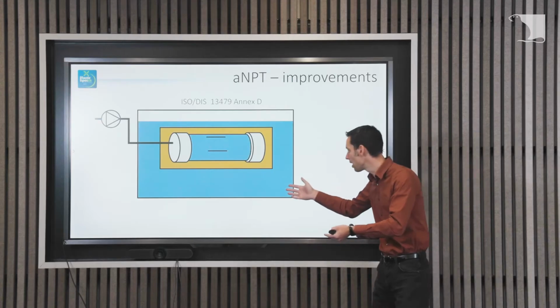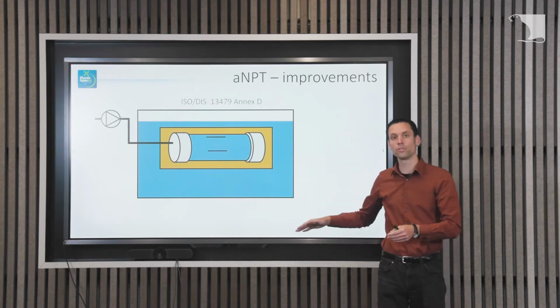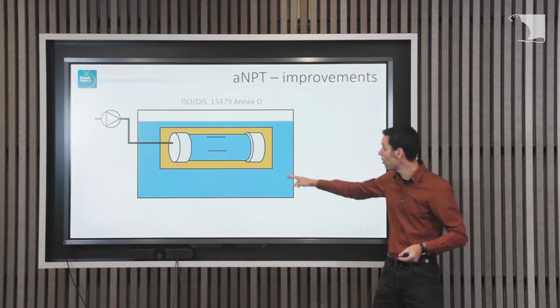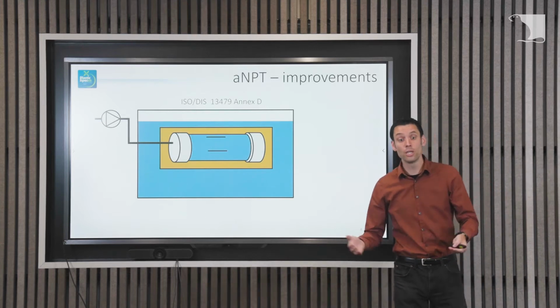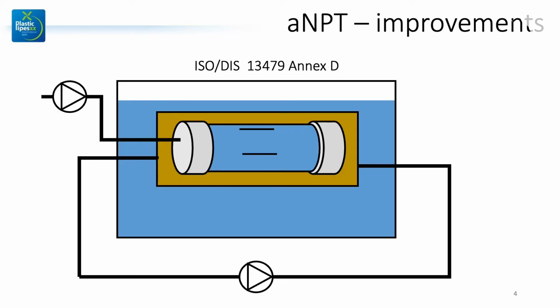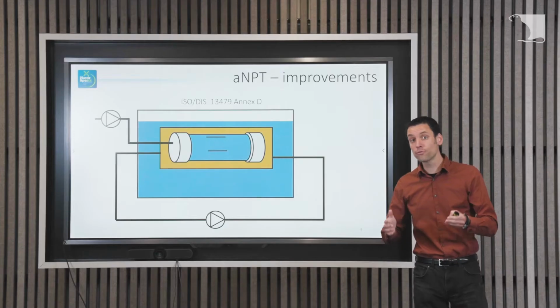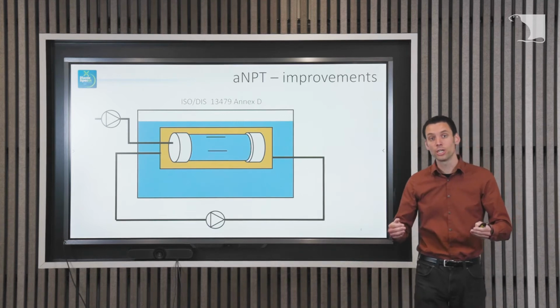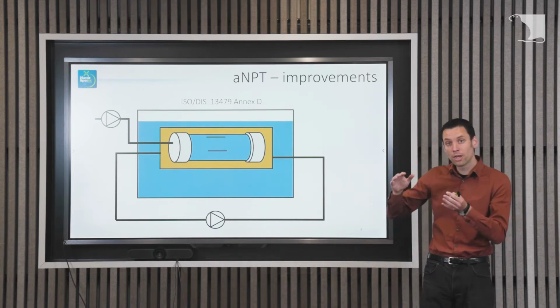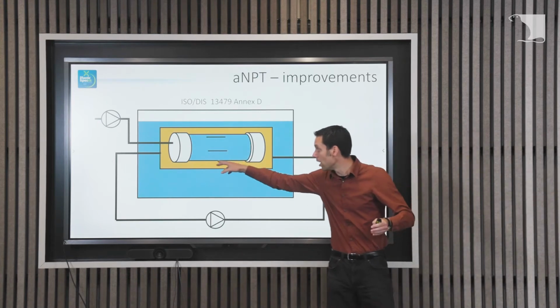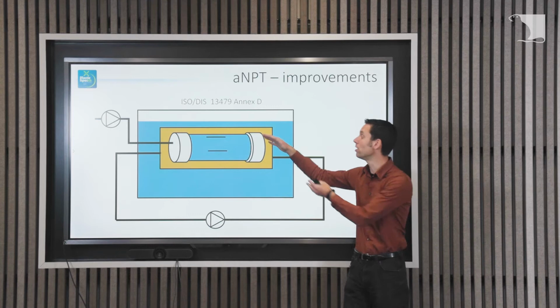The only point here is that the detergent also sinks to the bottom if you're not letting it flow. And normally in the water tank, it's all circulated because of the homogeneous temperature we need. But now within that smaller container, we don't have that circulation. So in this case, we added a separate pump to circulate the detergent solution inside that smaller container. But it's of course very important that it's homogeneous and that the detergent really reaches all the notches and is not only aggressive to the notches on the bottom side of the pipe and not on the top side of the pipe. So therefore we did some extra tests.